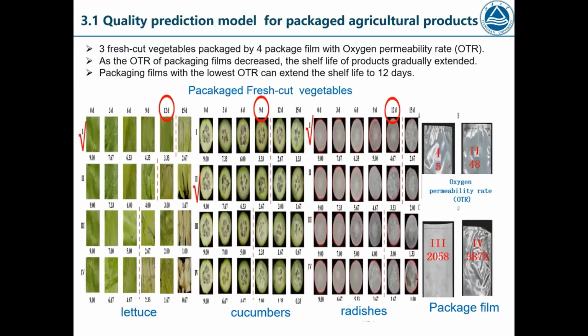During our study, 3 types of fresh cut vegetables were packaged by 4 kinds of packaging film with different OTR values. The results showed that when the OTR value of packaging films decreased, their shelf life extended. The longest shelf life was from fresh cut lettuce and cucumbers. Packaged by the film with the lowest OTR value, the shelf life could be extended to 12 days.